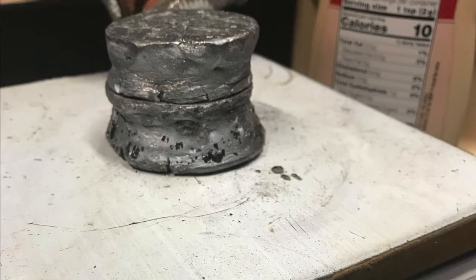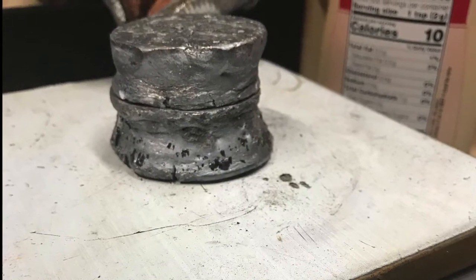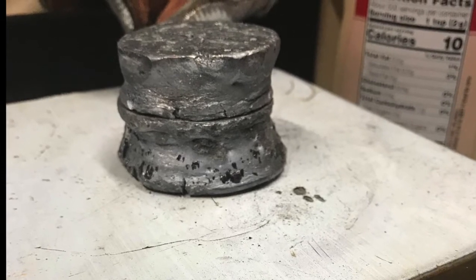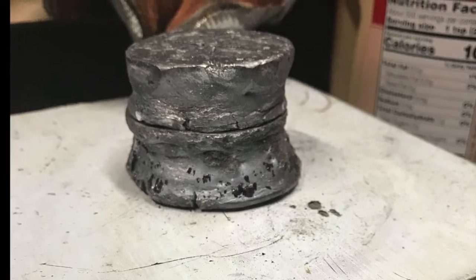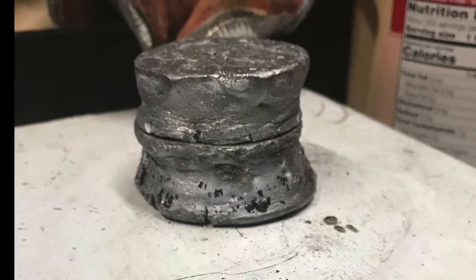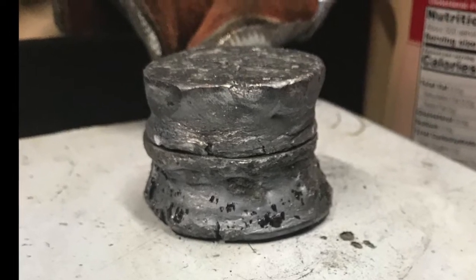This is it cleaned up and being weighed. It was about 1/3 of the weight of the concentrates, and from that we got about 3 ounces of gold. The prill is then cleaned and shaped so that it can go into the oven in what's called a cupel. Those dishes there are cupels.